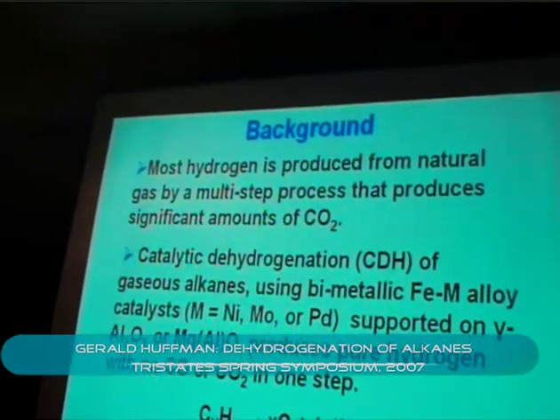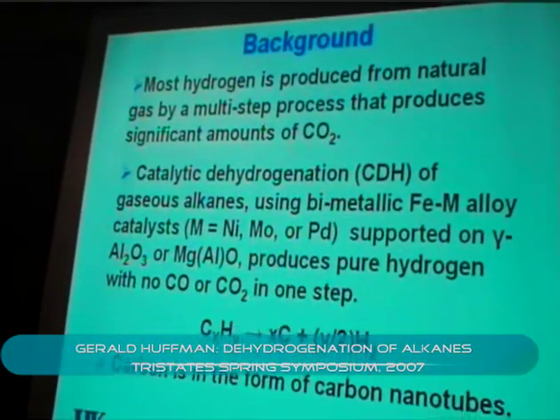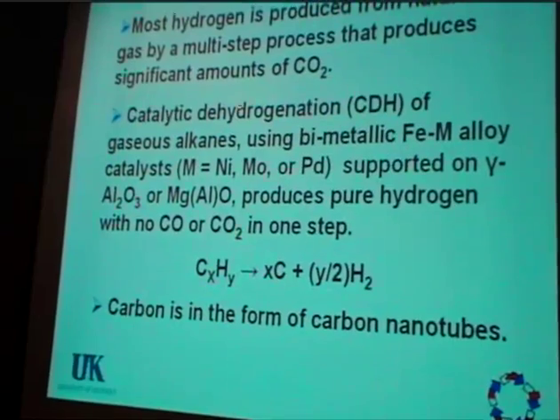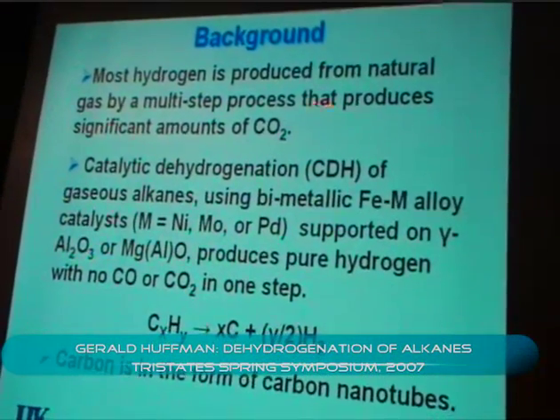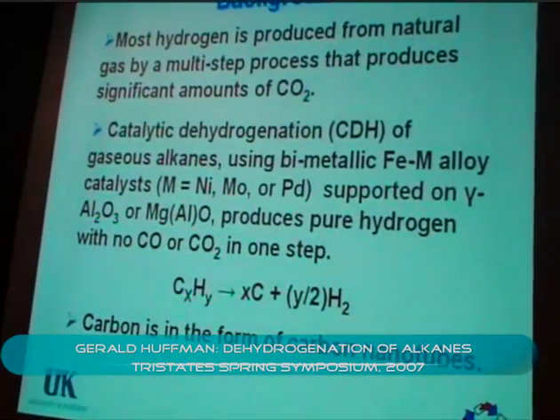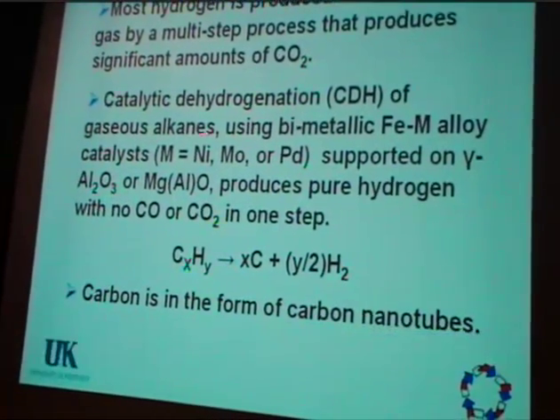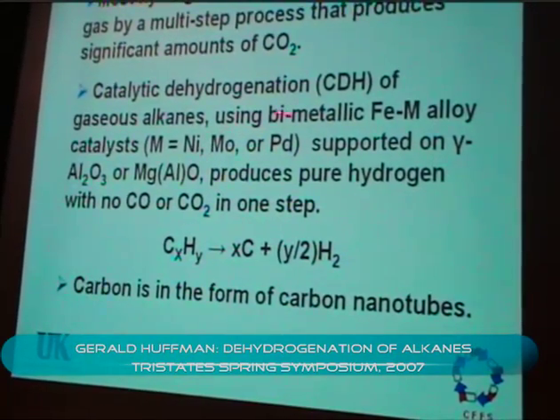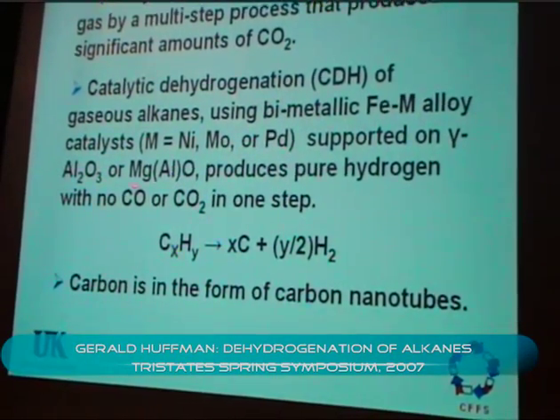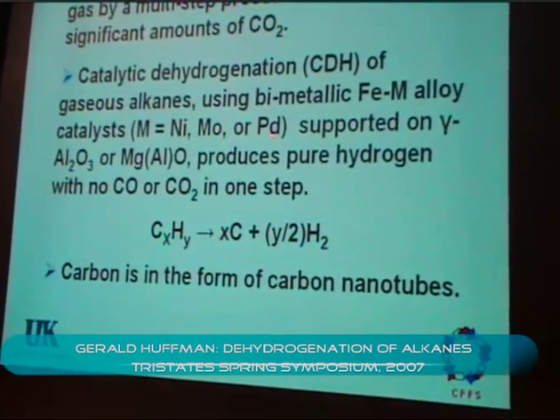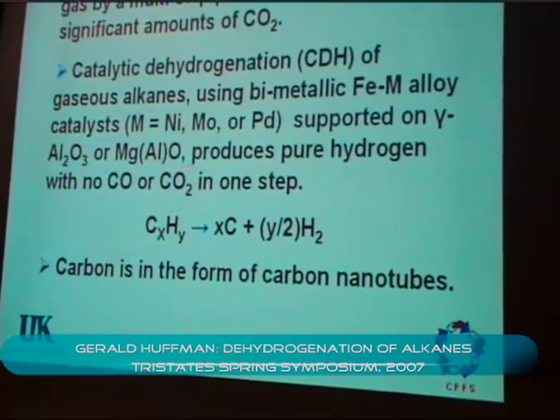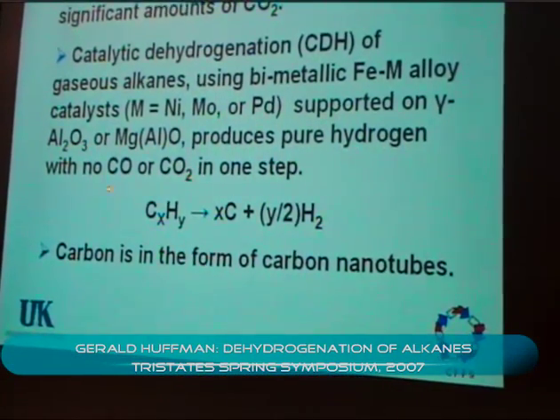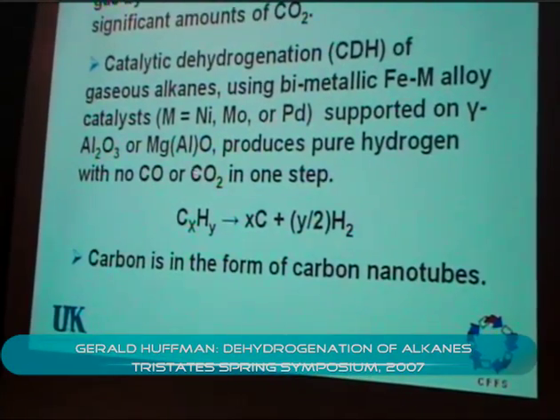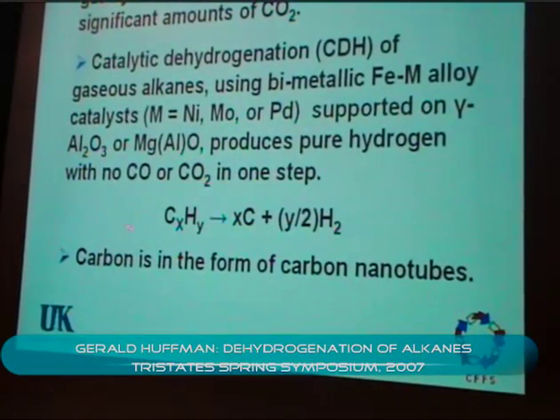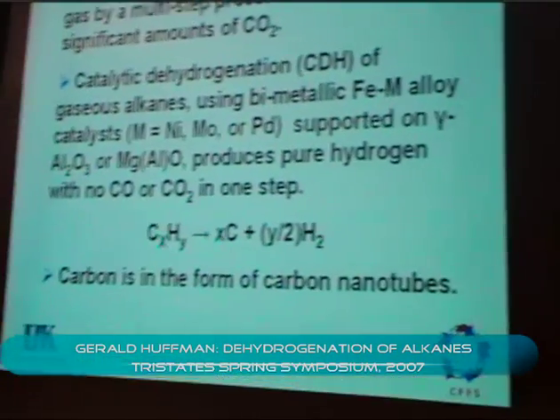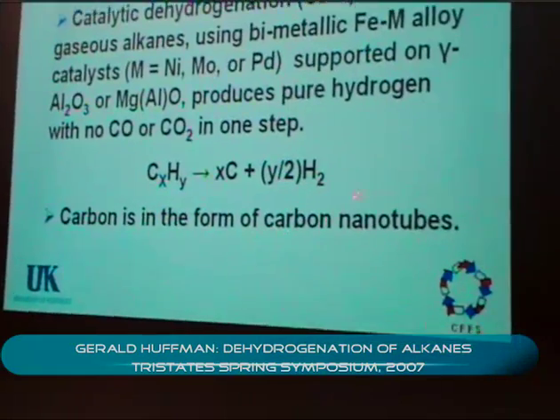Well, of course, most hydrogen is produced from natural gas by a multi-step process: steam reforming, water gas shift, PSA, etc. That does produce significant amounts of carbon dioxide. Catalytic dehydrogenation of gaseous alkanes using bimetallic iron-based alloys, the secondary element is nickel, moly, or palladium, on one of 2 supports, produces pure hydrogen with no CO, which poisons fuel cell catalyst, or carbon dioxide in one step. The reaction is very simple, and carbon is produced in the form of carbon